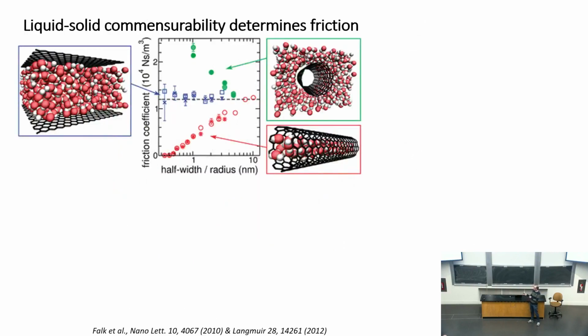In fact, the picture is more nuanced. For interior water, indeed, from molecular dynamics simulations, it's been suggested that slip length increases, or the friction coefficient decreases, as you go to lower diameter. But for water on the outside, it's quite the opposite. Water on a flat graphene sheet here doesn't show any dependence on radius, which here is just the distance between these walls.